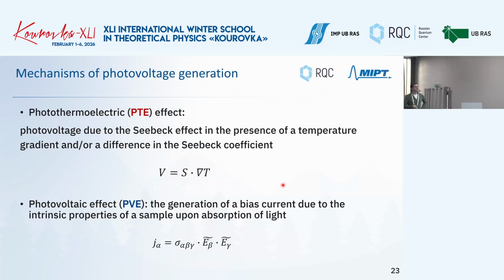Usually the mechanisms for photovoltage generation are the following: the photothermoelectric effect or the photovoltaic effect. In the photothermoelectric effect, you have photovoltage due to the Seebeck effect. As I mentioned, this delta T for graphene samples is very high, so the photovoltage is large, and that's why people are studying this. Another effect is the photovoltaic effect, the generation of a bias current due to the intrinsic properties of the sample. And it turned out that in our setup, it is not the photothermoelectric effect that is responsible for the detection, but the photovoltaic one.